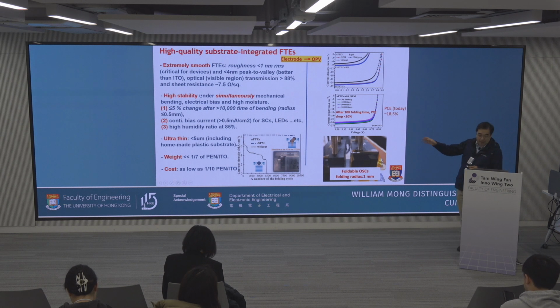Nevertheless, compared to conventional, we are much thinner. It depends on how you make it in the lab, or if you use some machine, just like a Mayer rod. Then you can make it as thin as 5 micron in our lab. The weight is 1/7 of PENITO, so that we can make it truly light. And the cost is just 1/10 of the conventional, making it potentially applicable. So this is a quick result.